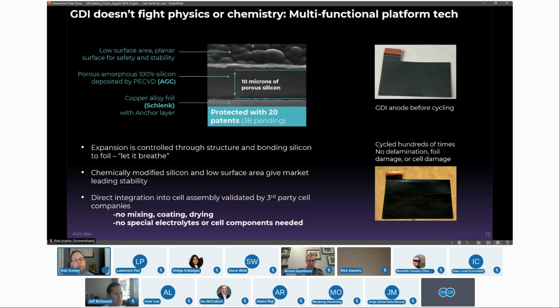And that's exactly what Amprius does too. Amprius solves it on an anode level. They make nickel silicide nanowires. They coat that with porous silicon, and that allows for expansion and contraction that doesn't cause the silicon to break up. What we did is a little different. We formed a partnership with AGC, the giant Japanese glass company, second largest glass company in the world, and Schlenk, one of the leading advanced foil providers in Europe.